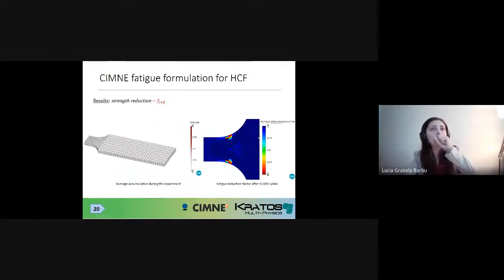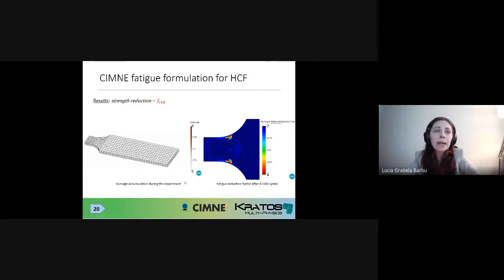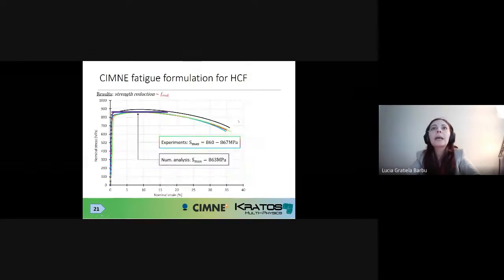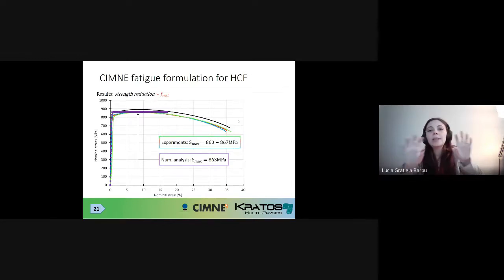Okay, so we started to do the same numerical simulation, where we applied the number of cycles, and then we broke the sample monotonically, and we took a look at what was the reduction factor after 31,000 cycles, and you can see here the areas which have reduced strength due to having applied these 31,000 cycles. Then we looked at the level of maximum stress that we obtained in the numerical simulation following this exact same load history, and we found that we had a really good agreement in this sense. So now we are working on designing the load sequence campaign experimentally. They are doing experiments, and when we receive the results, we also have to reproduce them.